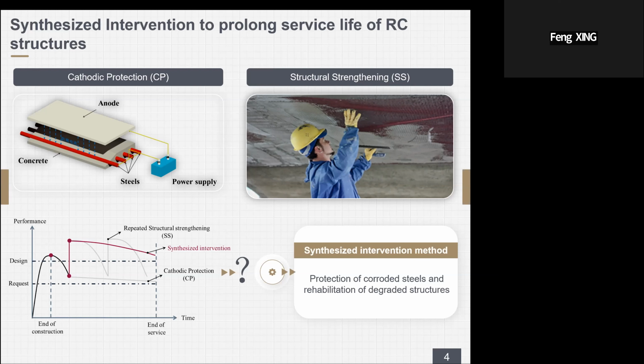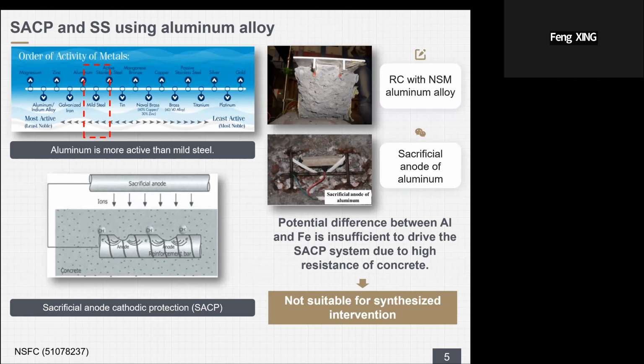On the other hand, cathodic protection also has a drawback. It is not able to recover the mechanical properties lost due to steel corrosion in the early stage. Therefore, it sounds like a natural idea to combine CP and SS to achieve synthesized intervention of both steel corrosion and mechanical behavior. The research started from 2008. We noticed that aluminum alloy is more active than mild steel, and it is a commonly used anode material for sacrificial anode cathodic protection. Therefore, we tried to use aluminum as both sacrificial anode and strengthening material. However, the result was not so exciting, since the potential difference between aluminum and steel is insufficient to drive the CP system due to the high resistance of concrete.